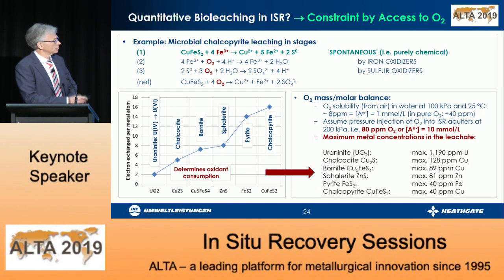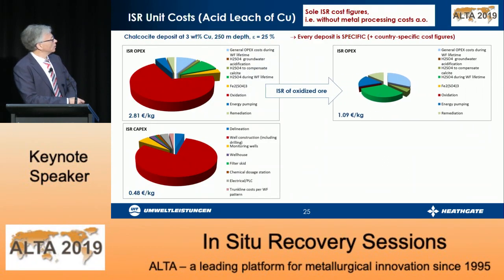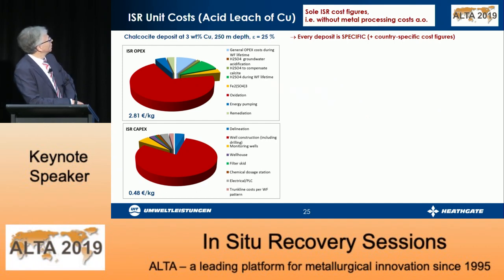This is shown here in some more detail, and I'd like to emphasize the electrons exchanged per metal atom for uraninite is quite favorable, but in the case of other sulfidic metals, you have to exchange a significant number of electrons. You consume a lot of oxidation potential, and this results in a particular estimate. If you inject 80 ppm O2 under pressurized conditions, this corresponds to a maximum metal concentration that can be leached theoretically. That's a stringent constraint. For uranium, it's quite favorable, but for the other sulfidic ores, it's a constraint that will impact the applicability of bioleaching as well.